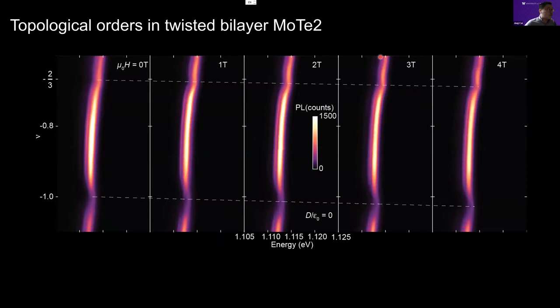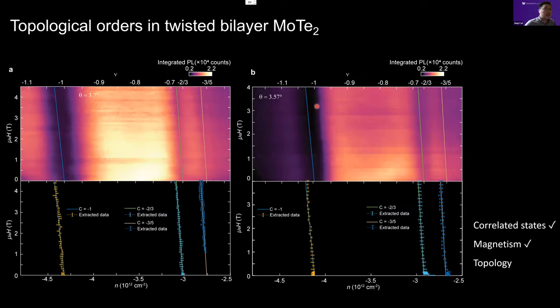Okay, the next step is to establish the topological property of this twisted bilayer molybdenum ditelluride. We can perform the PL spectrum that senses those correlated states as a function of magnetic field. You can clearly see a Zeeman-like shift in these two states. Now we can do a systematic analysis of this phenomenon by taking this map at many different magnetic fields and collapsing them into a single plot. What we can see is that indeed in these fractional states we see a dispersion, and this is actually quantized if you extract the peak position.